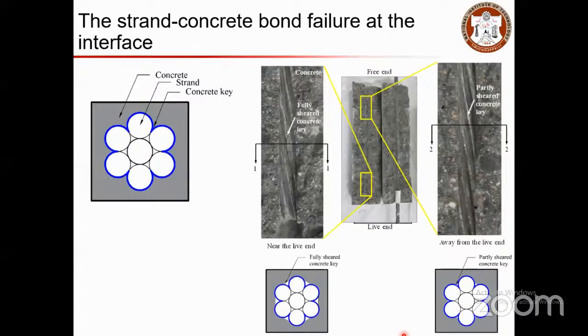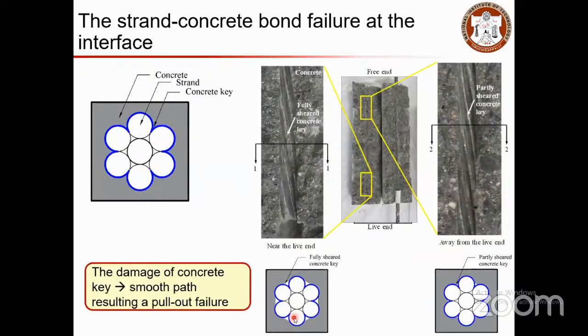For helical shaped strands embedded in concrete, the bond failure is different. You have a shear key formed, and as the strands are pulled out, these shear keys also get deformed. Partially the shear keys crack at the initial stage, and here you can see the shear keys are completely cracked, which gives a pipe formation through which the strands pass smoothly. The damage of the concrete key creates a smooth path, resulting in pull-out failure.